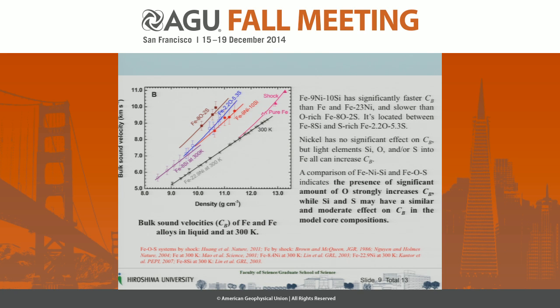The results also show nickel has no significant effect on bulk sound velocity, but light elements like silicon, oxygen, and sulfur all can increase the bulk sound velocity. A comparison of our iron-nickel-silicon system and the previous iron-oxygen-sulfur indicates that the presence of a significant amount of oxygen strongly increases the bulk sound velocity, whereas silicon and sulfur may have a similar and moderate effect on the bulk sound velocity in the model core compositions.